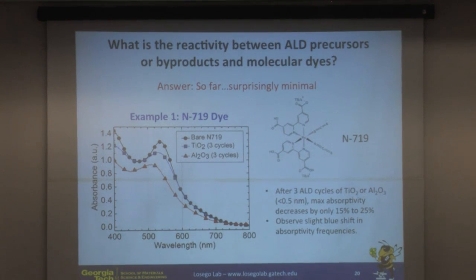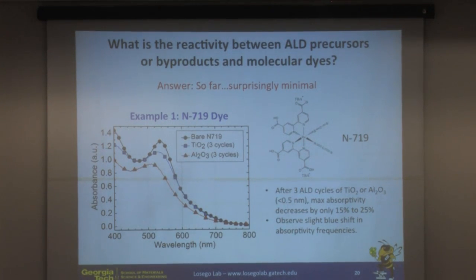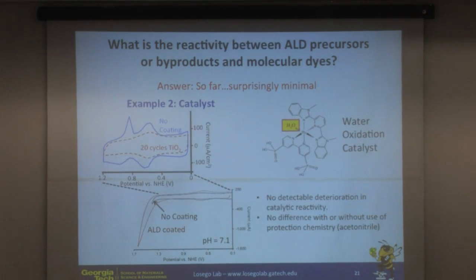Now, if we look at the UV-Vis absorption spectra, just where does this dye absorb light? That's its prime functionality. We see that the black curve is just the bare dye on a nanoporous substrate. And then if we coat with TiO2, three cycles, that's about 1.5 angstroms, or alumina, three cycles, which is about 3 angstroms, we still see fairly strong absorption and maybe a slight blue shift. So we do lose some absorption, but not that much, and a slight blue shift in the absorption. We believe that's some modification to these thiocyanate groups.